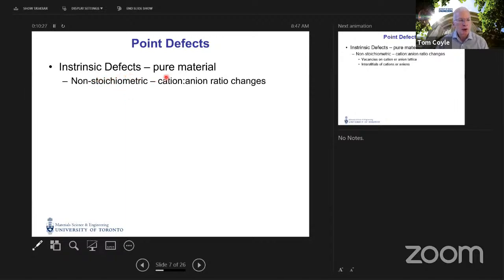Another category, still intrinsic, and therefore found in chemically pure materials, are non-stoichiometric defects. These are defects which result in a change in the ratio of the cations to anions. These are found in oxides where the cation can exist in multiple oxidation states. So titanium, for example, can exist as a +4 or a +3. And so to give a little bit of a clue as to where we're going, titanium oxide is a material in which these non-stoichiometric types of defects can occur. Vacancies on either cation or anion sites or interstitials of cation or anion sites.